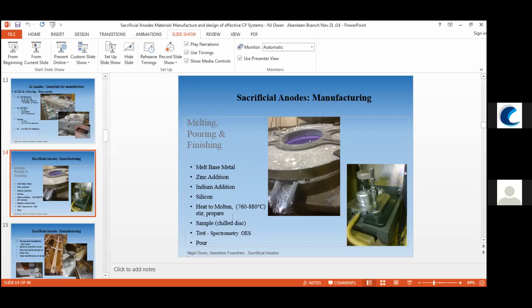You heat this molten metal to around 760, which is the sort of minimum melting temperature of this alloy with the 5% zinc in it, and stir it, prepare it, and make it homogeneous by stirring it. We can then sample that by just making a simple chilled disc, and we can then do some test spectrometry, of which a very fast method, which you can get a result of in 2 or 3 minutes, is by optical emission spectroscopy.